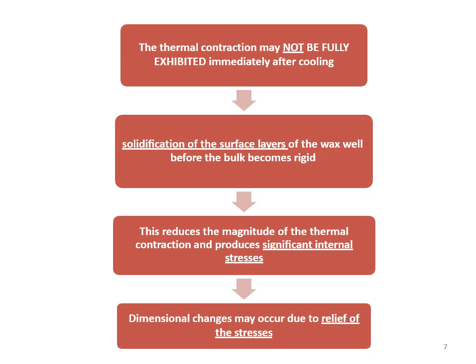Thermal contraction may not be fully exhibited immediately after cooling, followed by solidification of the surface layers of the wax well before the bulk becomes rigid. This will reduce the magnitude of the thermal contraction and produces significant internal stresses. Hence, dimensional changes may occur due to the relief of the stresses.